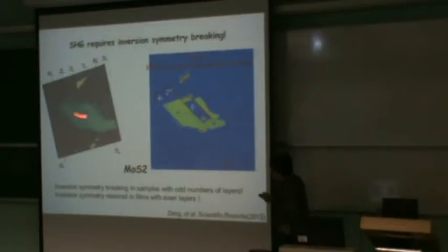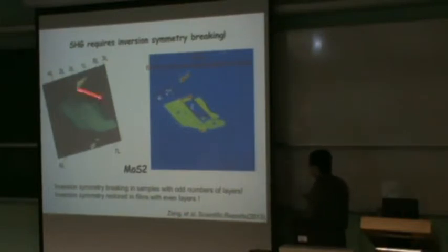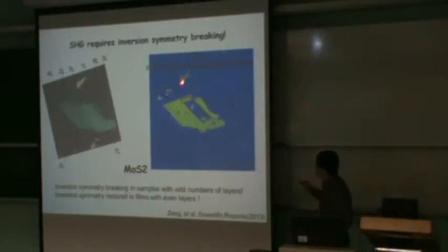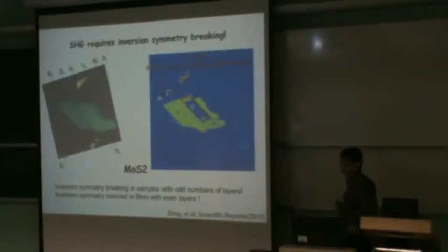That's very simple knowledge. And here is an example: you get a piece of molybdenum disulfide flake under optical microscopy. You can see the different thicknesses: monolayer, bilayer, trilayer and quadrilayer. Then you scan the whole sample with an 800 nanometer excitation, and collect the signal at 400 nanometer, which is double the frequency of the excitation. The second harmonic generation is the signal at 400 nanometers. You can see the strong signal comes from the monolayer, and all the even layers disappear from the second harmonic generation signal.